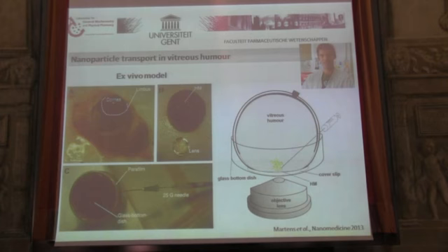Thomas Martens is the guy who developed this. So what we do is we go to the slaughterhouse, we have an eye of a cow, and what we do is we just take out the lens, so just the front part is taken out, and then you have a window into the vitreous without actually damaging the vitreous. And the vitreous does not leak out because the vitreous is enclosed by a limiting membrane, so it's actually protected. But you can image through this membrane.